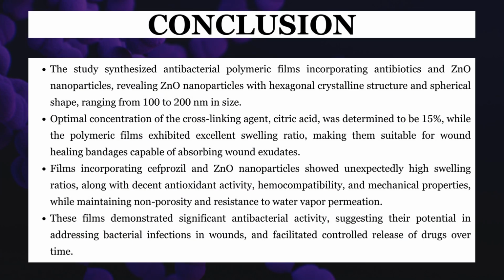Conclusion: the study synthesized antibacterial polymeric films incorporating antibiotics and ZnO nanoparticles, revealing ZnO nanoparticles with hexagonal crystalline structure and spherical shape, ranging from 100 to 200 nanometer in size. Optimal concentration of the cross-linking agent, citric acid, was determined to be 15%, while the polymeric films exhibited excellent swelling ratio, making them suitable for wound-healing bandages capable of absorbing wound exudates.